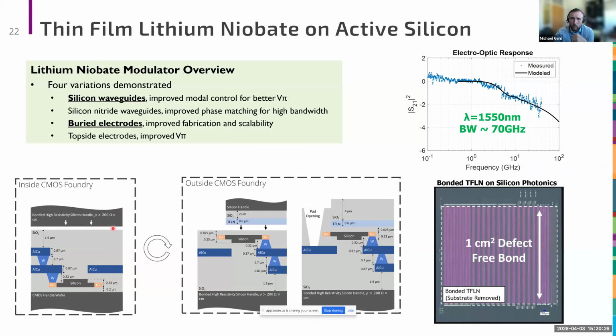We flipped the entire thing over and removed the original handle. And so now our waveguide is at the top of the stack with a very, very smooth, pristine surface here. And we bond our thin film lithium niobate onto that. And this bonding we do at sort of the chip level. You can see here an image of one of these devices where we've bonded roughly a centimeter square piece of lithium niobate across an array of modulators here. And with this, we've shown bandwidths on the order of 70 gigahertz.